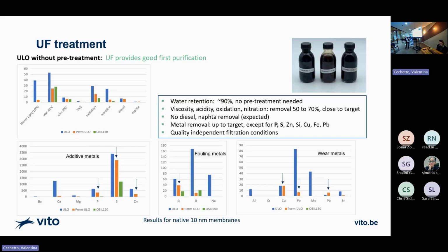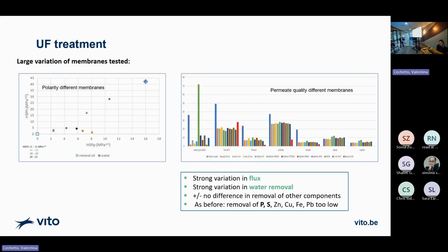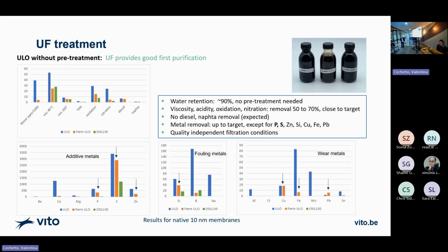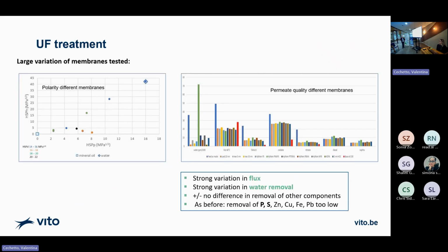As to the metals, you have metals from additives, from fouling, like from sand, the silicon there, or from wear, from your engine, iron, you see there. There's quite a good removal of the metals, but sulfur is not. It is probably very small, and phosphorus is also one of the difficult elements. These were results of native 10 nanometer membranes, which we use a bit as a benchmark. But we used, like I said, lots of other membranes.